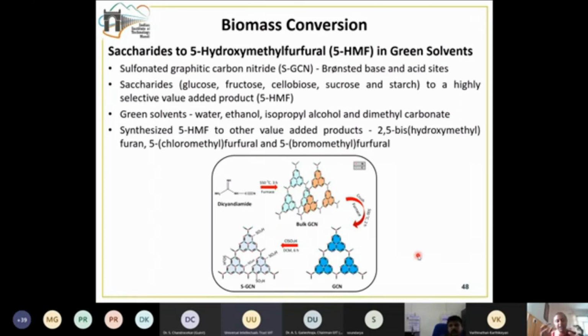So we took graphitic carbon nitride and functionalized it with sulfonic acid groups to prepare sulfonated graphitic carbon nitride, so that the material has both Bronsted base and Bronsted acid sites. We used this material for the conversion of different saccharides, from monosaccharides to polysaccharides, into a specific and highly selective value-added product, 5-HMF. We used several green solvents ranging from water, ethanol, isopropyl alcohol, and dimethyl carbonate. The synthesized HMF was converted further into other value-added products such as 2,5-bis-hydroxymethylfuran, 5-chloromethylfurfural, and 5-bromomethylfurfural.